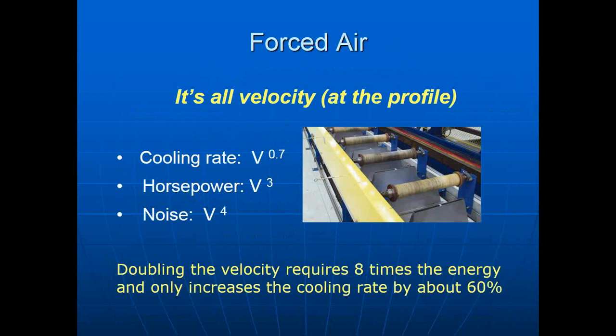There's a couple of key formulas that I listed there. Cooling rate is velocity to the 0.7 power. But horsepower is velocity cubed. And noise is velocity to the 4th power. At some point, these turn into whistles. What these numbers do is they give us a practical maximum of forced air of about 10,000 feet per minute. If you're running much faster than that, your horsepower gets crazy, the nozzles get very noisy,